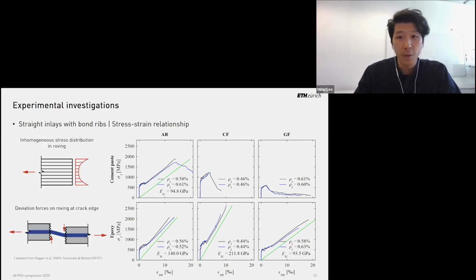And in textile reinforcement, this has usually 2 main reasons, which have been reported in literature. One is that the stress distribution in a roving is normally inhomogeneous, leading to that we cannot exploit the full strength of the rovings. Another reason is that deviation forces on the crack edges reduce the tensile strength since they introduce highly concentrated lateral loads.